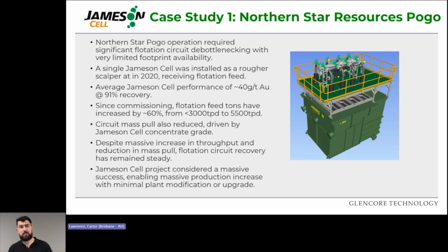So, summing up case study number 1, Northern Star Pogo needed to debottleneck their flotation circuit with very limited footprint availability. A single Jameson cell, which is pictured on the right there, was installed as a rougher scalper in 2020, receiving the flotation feed. The average Jameson cell performance since then has been 40 grams per ton of gold at 91% plus recovery.